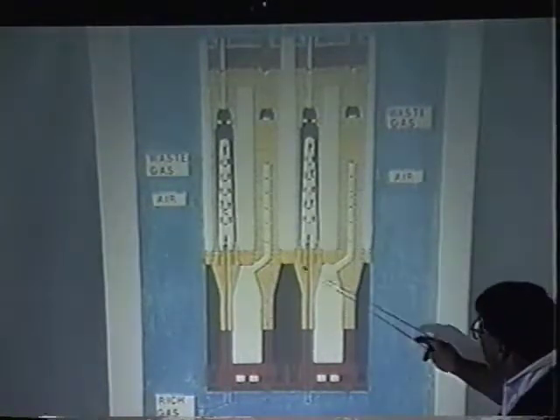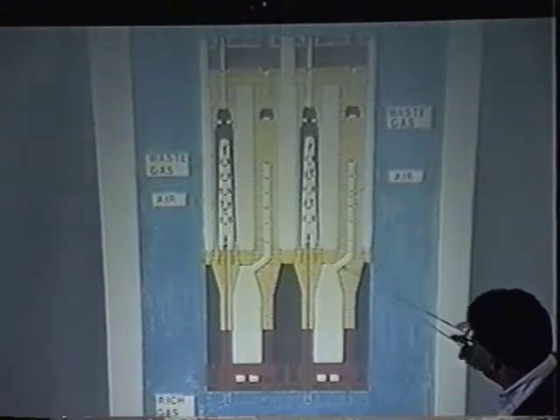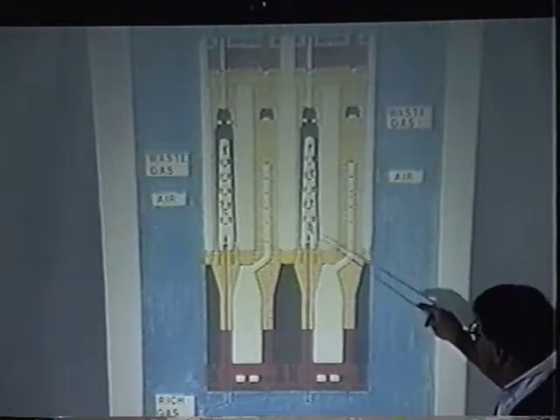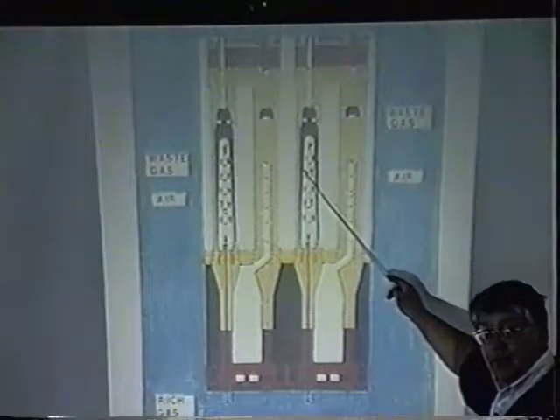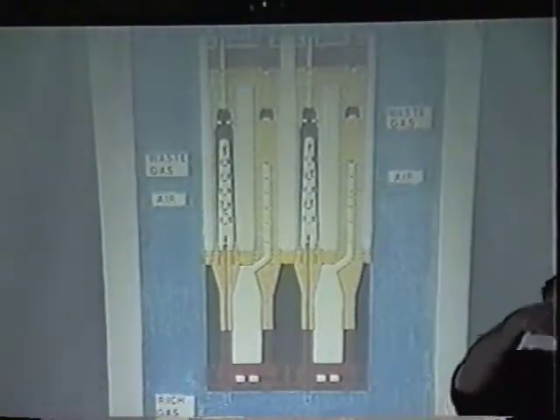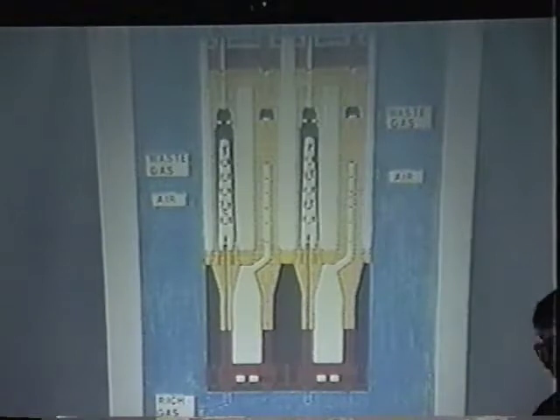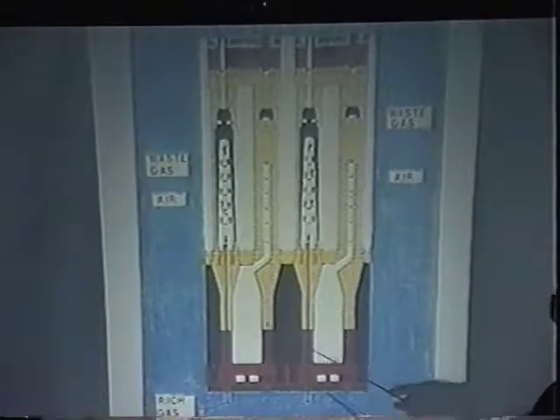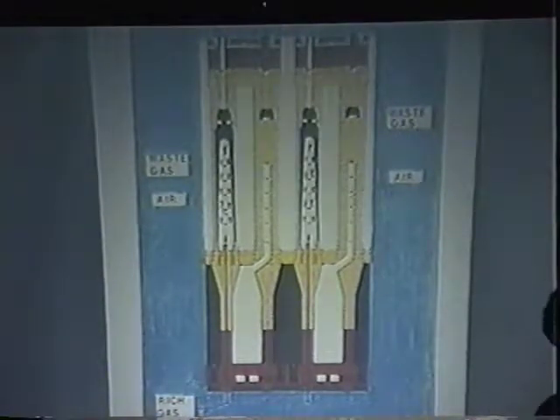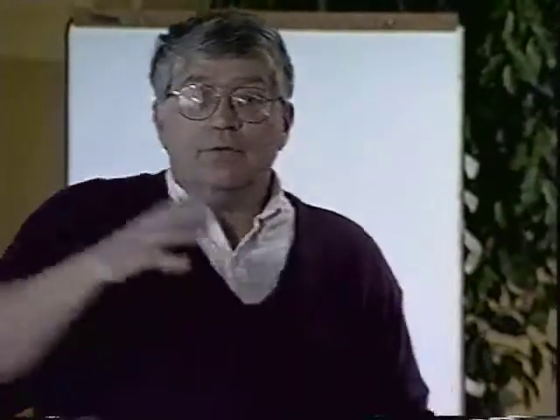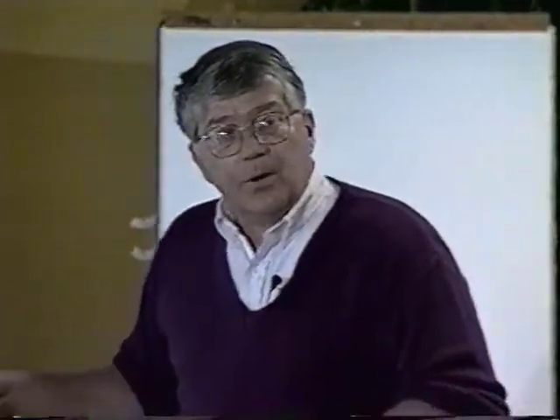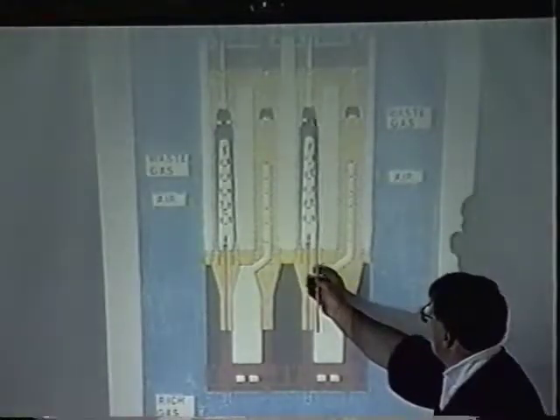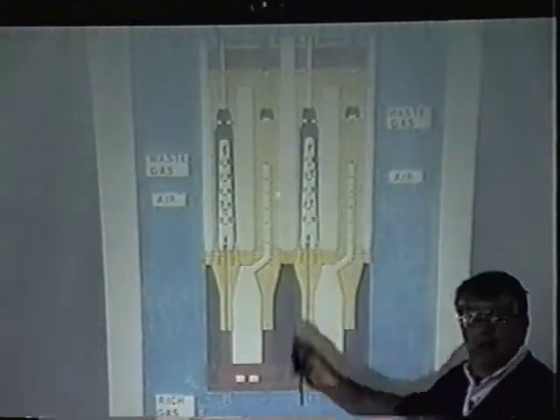But we mix, as you can see, these air ports, and this is not a very good drawing, but the gases come in, mix with the air in one flue, then the waste gas, the product of combustion, goes down through the other flue and comes out the adjacent regenerator, okay, and out the stack. Then that regenerator heats up, and we reverse every 20 minutes, and we use the other regenerator to heat the air. So every other flue is burning, and then on the off side, every odd flue is burning. And that heats the coke from the wall, both walls, in.